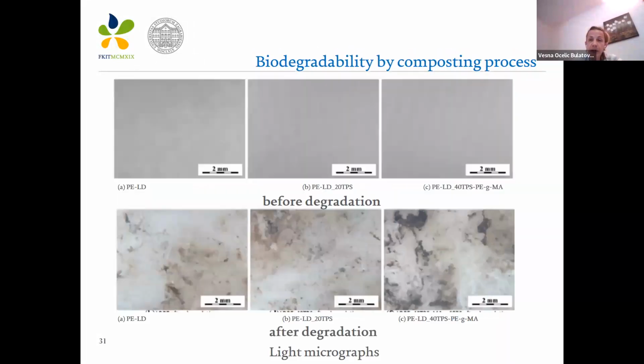On this slide, we can see the morphology of the samples before and after composting, monitored by light microscope. On LM micrographs, we see evidence that blends with and without the compatibilizer, up to 20% of TPS, were compact with minimum degradation. In contrast, the blends with high TPS content were completely degraded during the composting process of 60 days. For low TPS loading, TPS particles were maintained within the olefin matrix with slowed down degradation. We can say that for the high loading of 50% of TPS, a continuous polysaccharide phase was formed, enabling complete degradation.